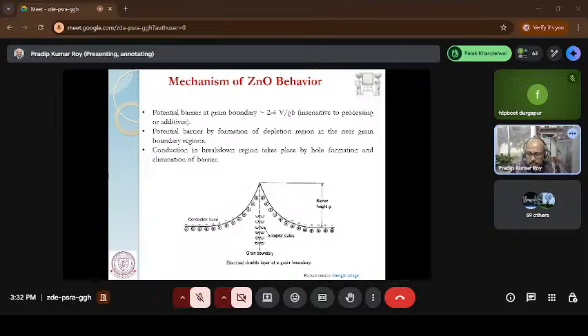Now, when the surge goes back, mostly it is found that the electric field across the grain boundary decreases, impact ionization stops, tunneling probability drops drastically, and all the trap charges at the grain boundary reform and again create the depletion layer. That means again the potential barrier is increasing. So that Schottky barrier on both sides is increasing, and again it becomes an insulator.